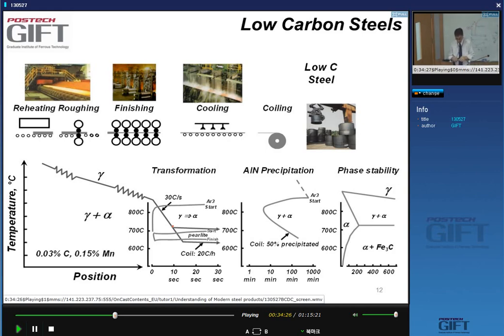That's one thing. The other thing is, of course, carbon. We know that the carbon is not soluble in the ferrite, so it's got to precipitate out. And we want it to precipitate out because we do not want solute carbon in our ferrite. Why? Because it gives me this aging. And why is this aging a problem? Because you get these Luders bands. So you have to decide here.